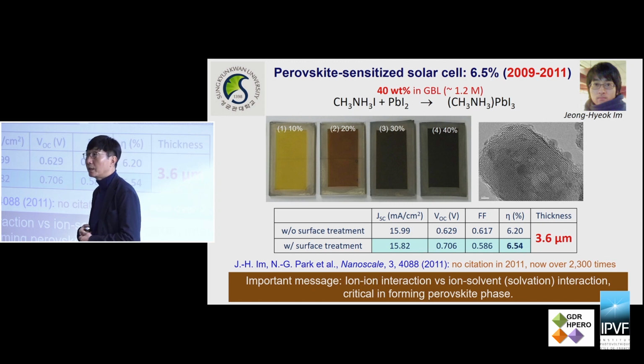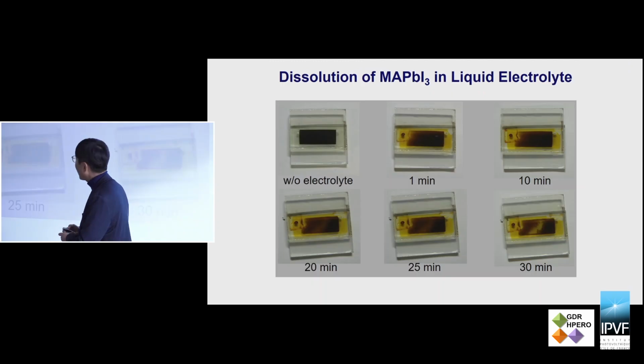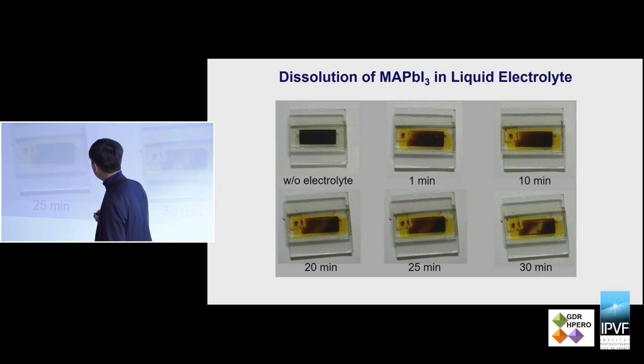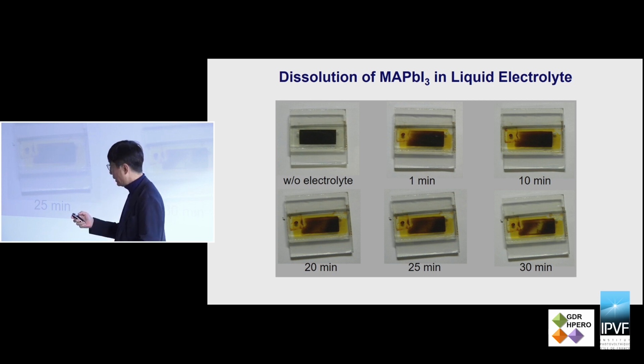But this is still in the dye-sensitized solar cell structure, meaning that we still have the liquid electrolyte. That means we cannot guarantee the stability in the presence of a polar liquid electrolyte. As you see here, this is a typical dye-sensitized solar cell structure, sandwiched between two FTO conducting glasses. And the black color comes from the methyl ammonium lead iodide. If you inject the electrolyte, then in a few minutes some perovskite is dissolved quickly. So it is not a useful material for a liquid electrolyte-based solar cell.